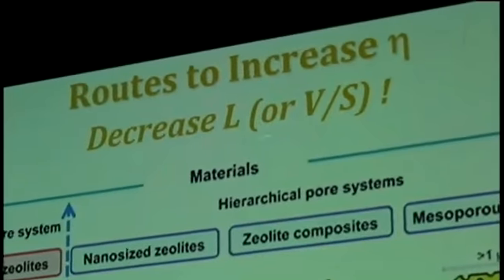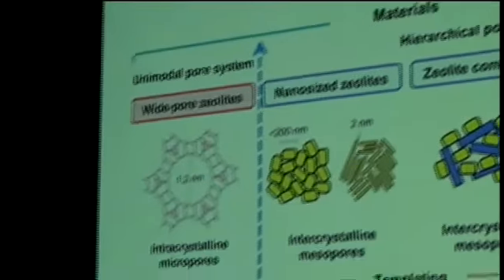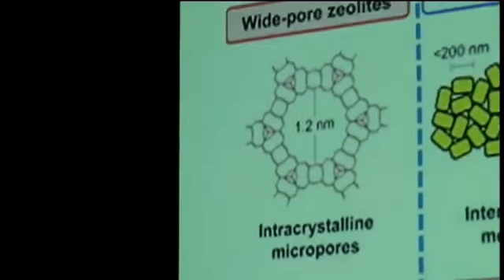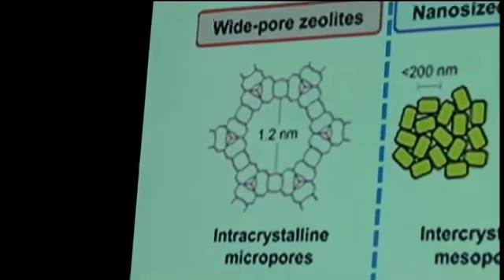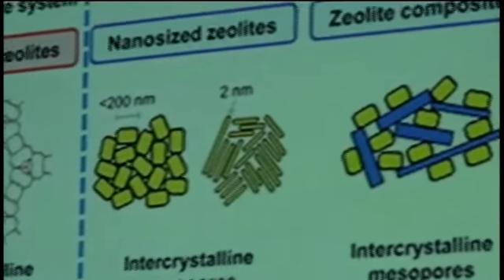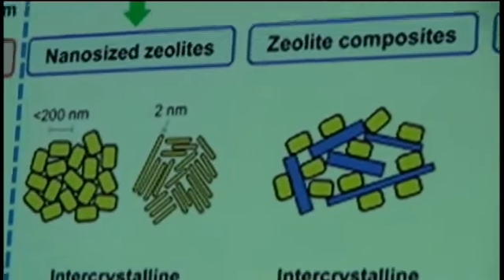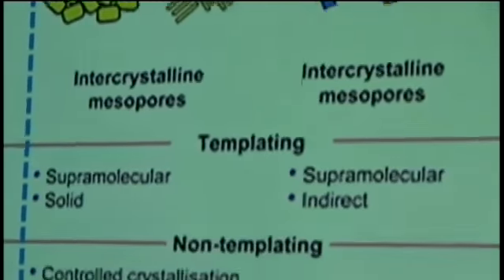Now, once you have grasped the Thiele modulus concept, it's obvious that if you want to have zeolites more efficient, you have to decrease the diffusion path length, or in another way, you have to change the volume to surface ratio. There are many ways to do that, and this has been relatively elegantly summarized by Javier Pérez-Ramírez. They are so-called bottom-up techniques.